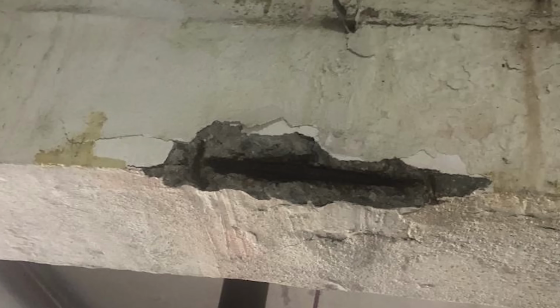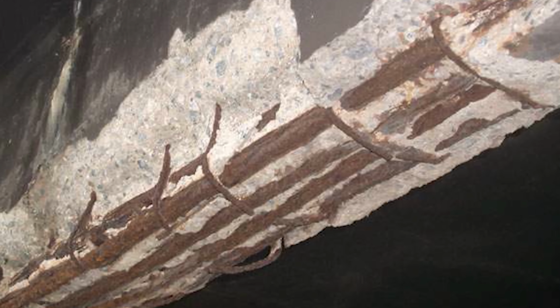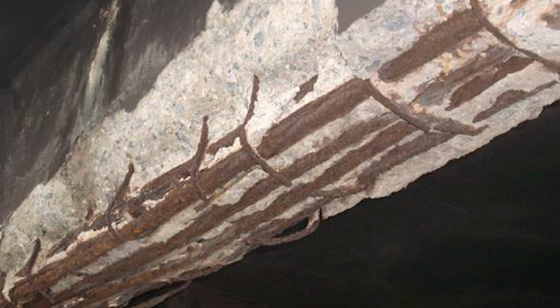But why does the presence of these external agents harm the steel inside the concrete so much? Steel is naturally protected by the high alkalinity of concrete, which forms a passivating layer around the bars. This layer prevents the metal from oxidizing. The problem is that over time, carbon dioxide reacts with the components of the concrete in a process called carbonation. This reaction lowers the pH of the material and destroys the protective layer of the steel. When this happens, the steel starts to oxidize. Rust takes up more volume than the original steel, so it's as if the steel starts to swell inside. This increase causes internal stresses, which end up creating visible cracks in the concrete. As corrosion progresses, entire parts of the surface layer can come loose, forming what we call spalling.